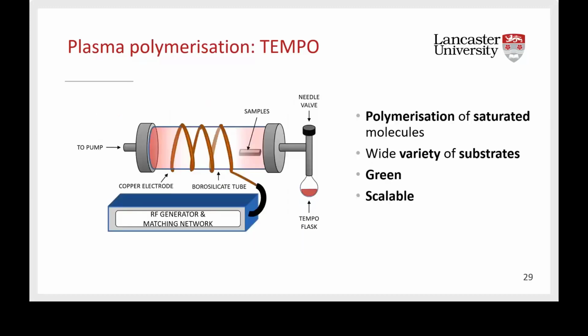However, we have a technique called plasma polymerization. This technique can be used to polymerize even saturated molecules like TEMPO. So it consists of basically a borosilicate tube that is filled with the gas of the monomer, so in this case TEMPO gas, and with an electric field we create a plasma, so that if a sample is placed in the plasma, it will be completely coated by the molecule, in this case TEMPO.